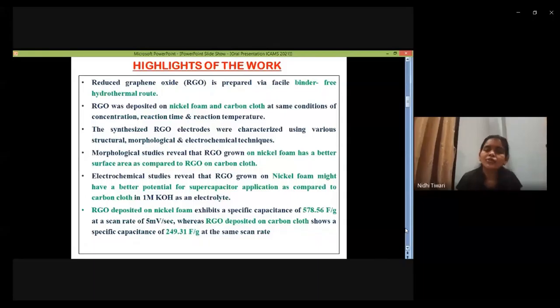The highlight of the work is that RGO here is prepared via a binder-free hydrothermal route. By using the hydrothermal reaction, we have deposited RGO on nickel foam and carbon cloth at the same conditions of concentration, reaction time and reaction temperature. Only the substrate change is there to study the comparison between the two. All the other parameters are kept the same.